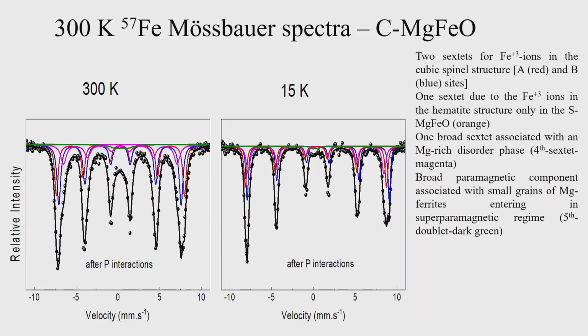A disordered phase. This magenta, disordered phase. And this broad paramagnetic component, that's small grains, ferrite. So okay, you put an excess of magnesium, you do not have hematite, you have small grains ferrite. It's quite interesting material. It's interesting to see that you have to put an excess of magnesium to get rid of the hematite.